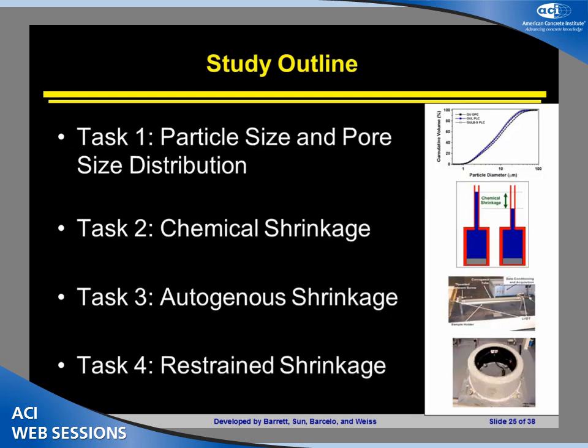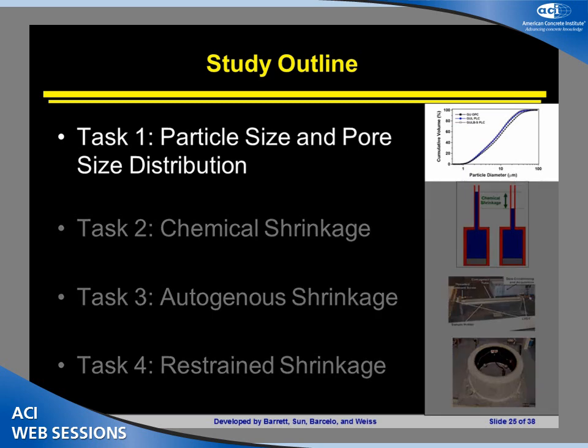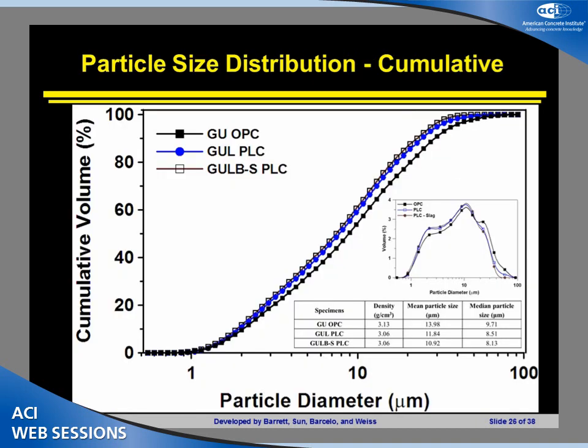All right, so to talk a little bit about this, I want to show particle size distribution, talk about reactivity, talk a little bit about shrinkage, and then the cracking potential. So the particle size distribution, again, I want to compare and contrast this to what you saw maybe 10 slides ago. I pointed out when we looked at those particle size distributions, we said in a conventional system, if you change the Blaine fineness, that curve sort of marches over to the left as it gets finer.